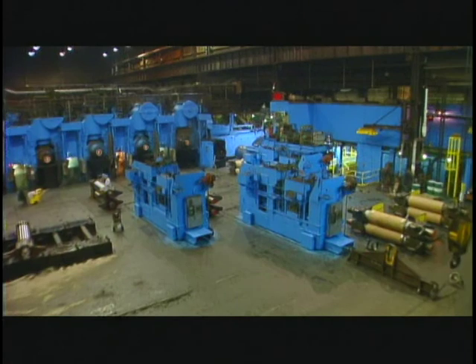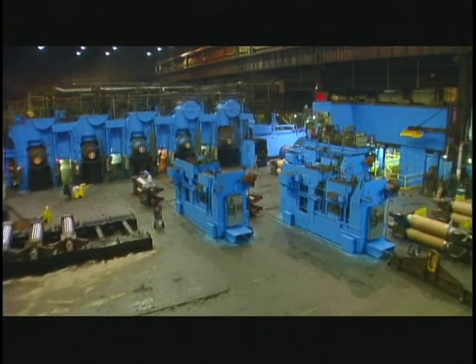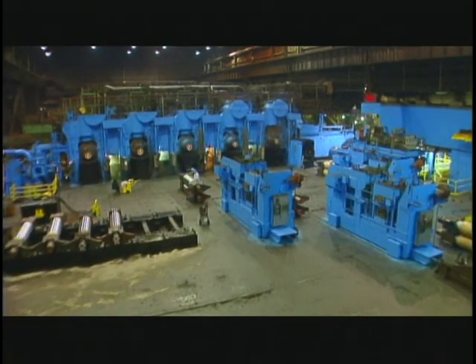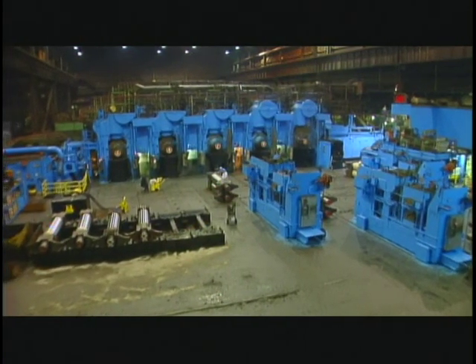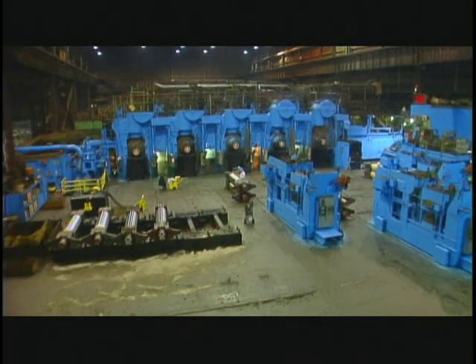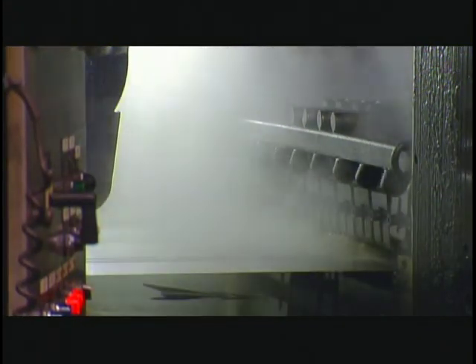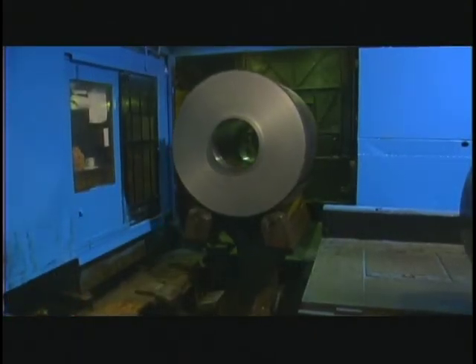Here at the 5-stand tandem mill, which is a computer-controlled mill, we use 3 X-rays to measure center line gauge, a shape roll after the last stand to monitor shape flatness. Here in the pulpit, we monitor how the computer is controlling the mill, and during the process of reducing a strip, I like to think of it as rolling cookie dough and a taffy pull to reduce the strip to customer specifications. And once it exits the mill here, the strip is too hard for customer use, so it has to go to downstream processing to get the right specs for customers in use.